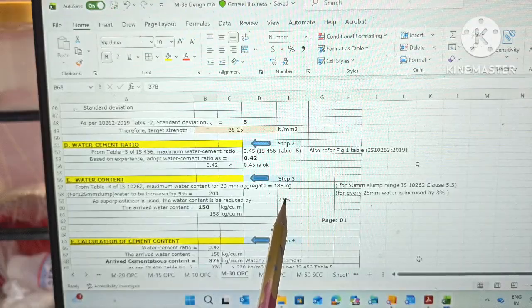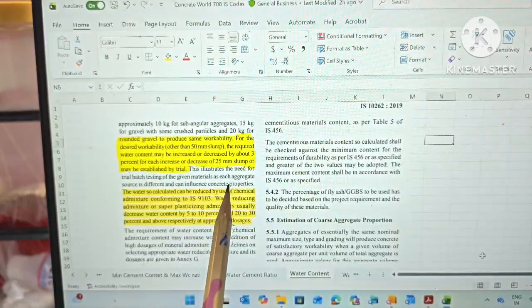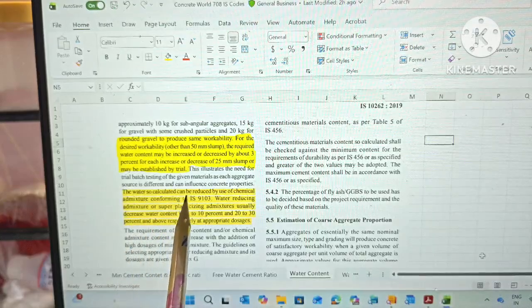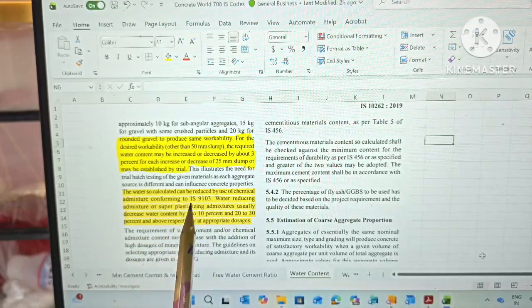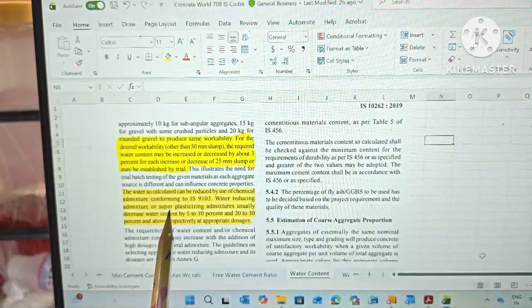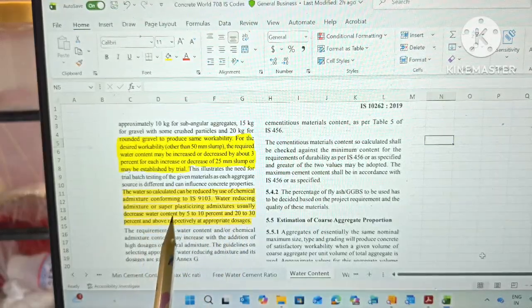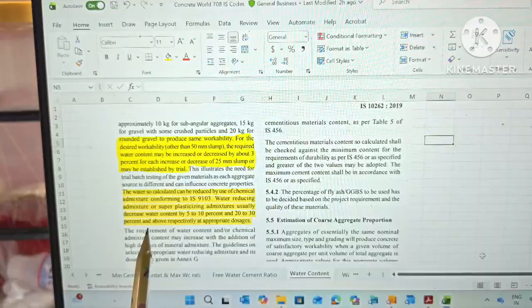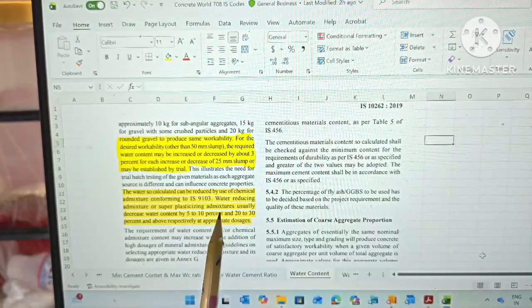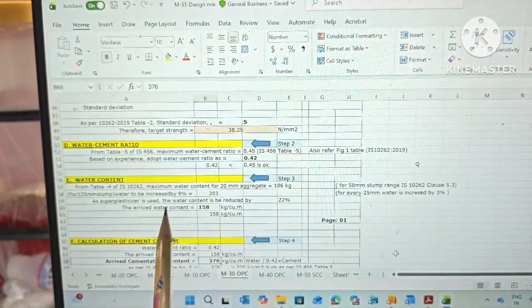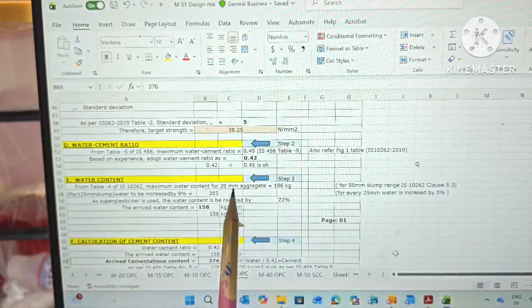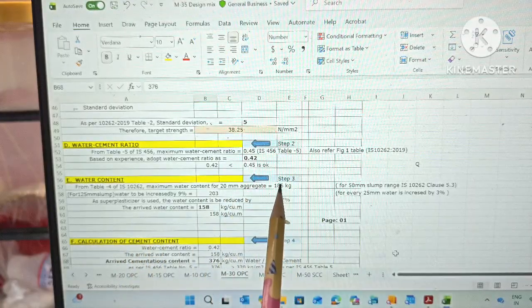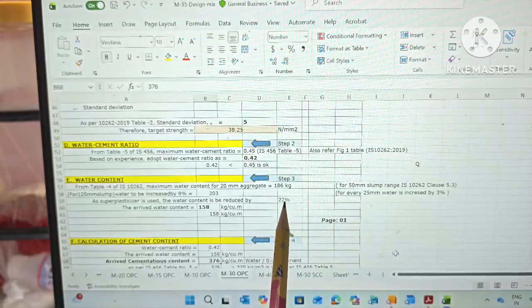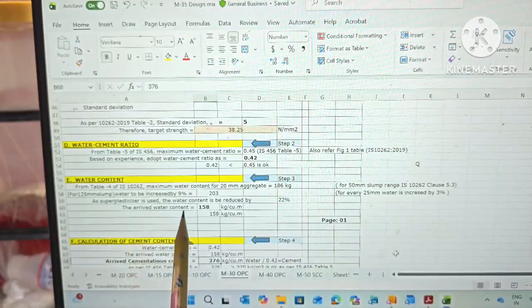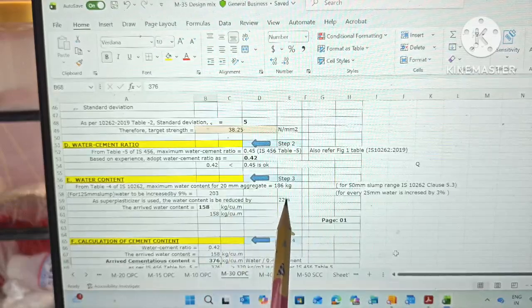So let me take you to the table. As per IS 10262, the water calculated can be reduced by the use of chemical admixture conforming to IS 9103. Water reducing admixture or super plasticizing admixture usually decreases water content by 5 to 10% and 20 to 30% and above respectively at appropriate doses. It means that if we use super plasticizer we can get 20 to 30% water reduction. So we have decided on 22% water reduction. So now our final water content will be 203 minus 22% of 203, that is 158.